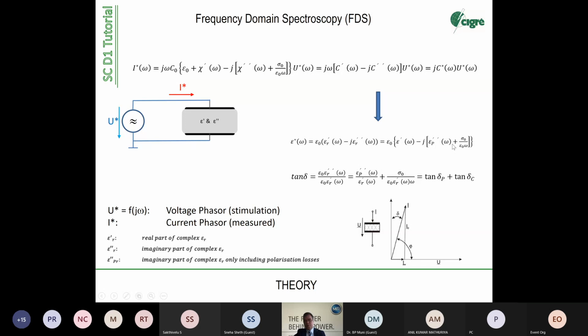The conduction part is given here. Both are depending on frequency. And so derives the tangent delta. Tangent delta is also known as loss factor. And the loss factor can also be split into the polarization part, so it's the dipoles where you lose energy by friction, and you have also a loss by conductive mechanism. So it's a very clear and comprehensive theory behind, and it's just about the evaluation of the complex permittivity.